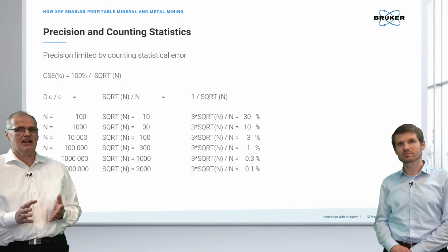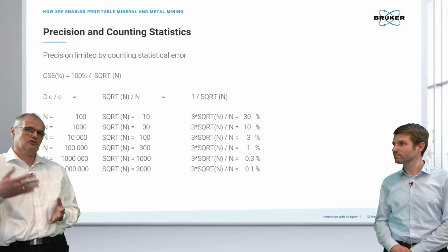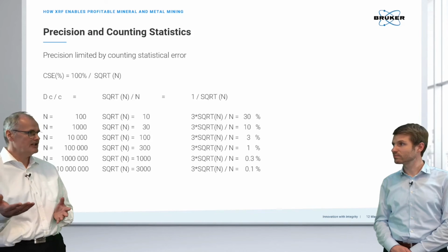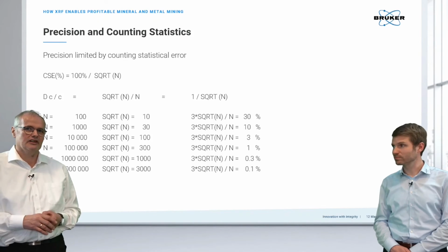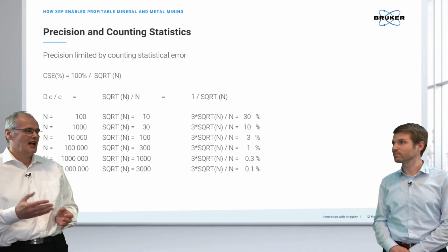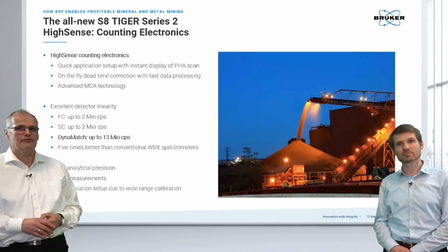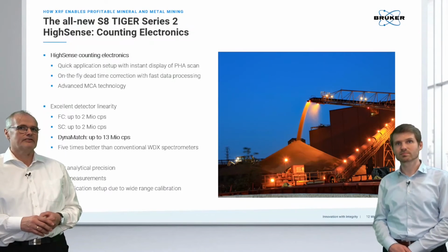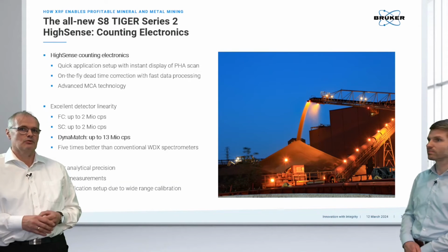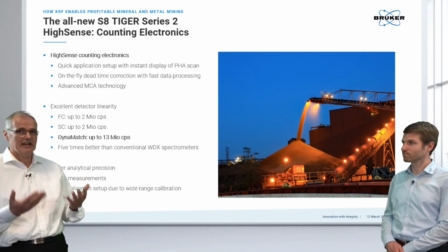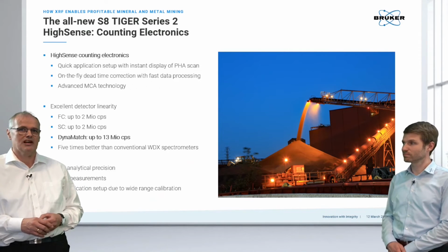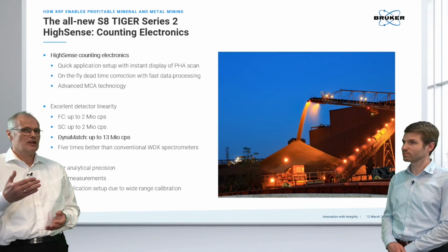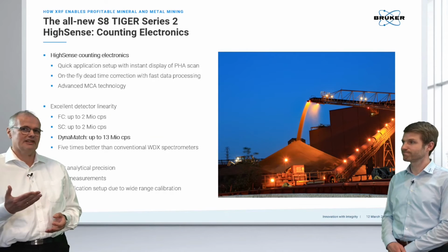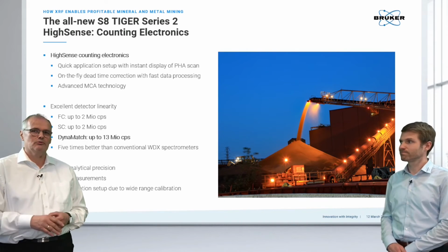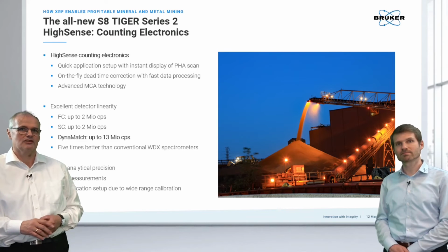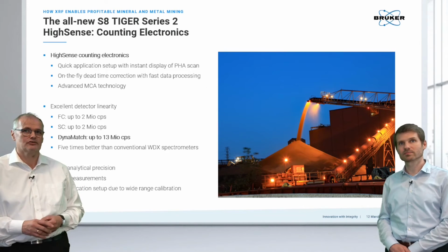And this shows exactly why we are now talking about 50 watt for ED, 400 watt for the benchtop WD, and now we are moving forward to up to 4 kilowatt with our S8 Tiger, which means that we are putting a higher excitation power into the sample. And of course, when we have a detector which can deal with this high count rate, then we are achieving very high precision. So we call this high sense counting electronics.